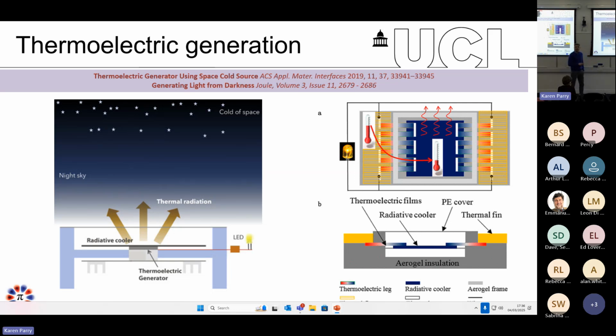In a thermoelectric material operating under radiative cooling, it's the opposite. It is now the cold side of the thermoelectric material that's exposed to the universe, and by reducing its temperature, you can actually generate electricity even at night. Now, there have been some really nice studies where they try to co-harvest, if you want, the 2 main thermodynamic resources, the sun and the universe, by exposing the hot side to the sun and the cold side to the universe. And this is very important because a lot of the times we're talking about competition. All of them occupy areas. So, by synergistically taking advantage of these 2 resources, there's no competition anymore, and you can improve the efficiencies even more.